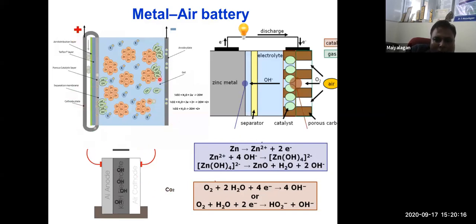You can see how the zinc is there. This is an anode plate. Zinc is the anode, and this is the cathode. Oxygen gets in, goes through the channels, and zinc ions form. So this is the anode oxidation: zinc anode oxidation takes place. At the cathode, oxygen reduction and evolution reactions take place. If you change the metal from zinc to lithium, it's a lithium air battery. If you change to iron, it's an iron air battery. If you change to aluminum, it's an aluminum air battery.